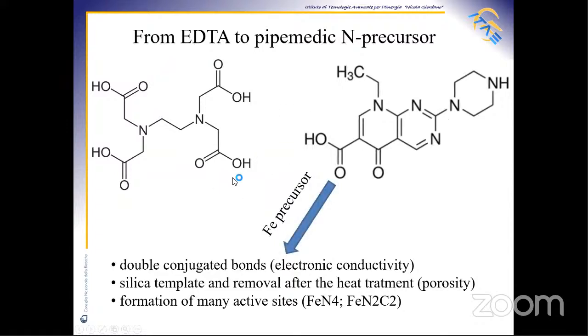Here, the nitrogen precursor is different from EDTA. Now we have a pipemidic acid precursor. And after mixing it with iron precursor and after heat treatment at 900 degrees centigrade, we obtained this structure characterized by double conjugated bonds for the electronic conductivity. This synthesis was done with the silica template and its removal after the heat treatment. And we have also the formation of many active sites, such as Fe-N4 and Fe-N2C2.